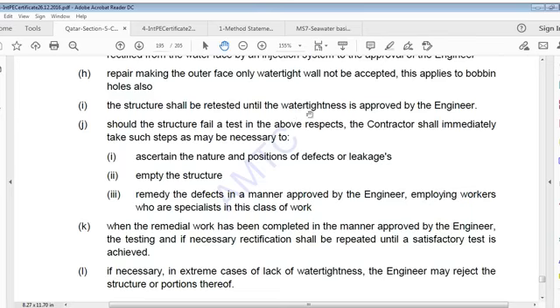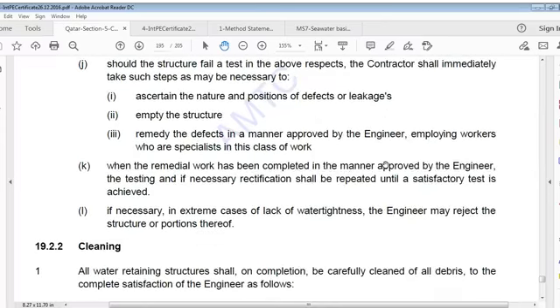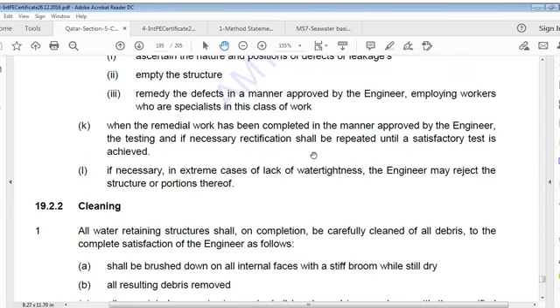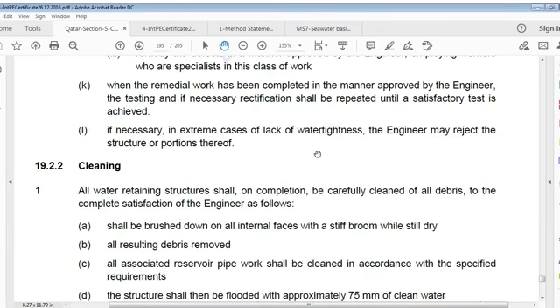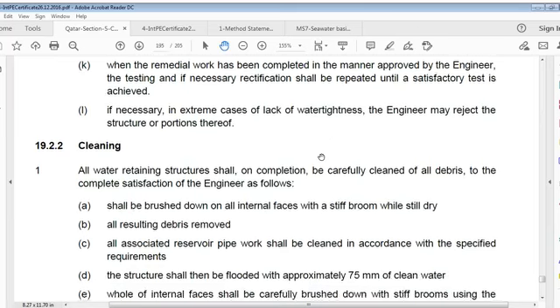Should structure fail a test in above respects, contractor shall immediately take steps as may be necessary to ascertain nature and positions of defects or leakages, empty structure, remedy defects in a manner approved by engineer, employing workers who are specialists in this class of work. When remedial work has been completed in manner approved by engineer, testing and if necessary rectification be repeated until satisfactory test is achieved. If necessary, extreme cases of lack of water tightness, engineer may reject structures or portions thereof.